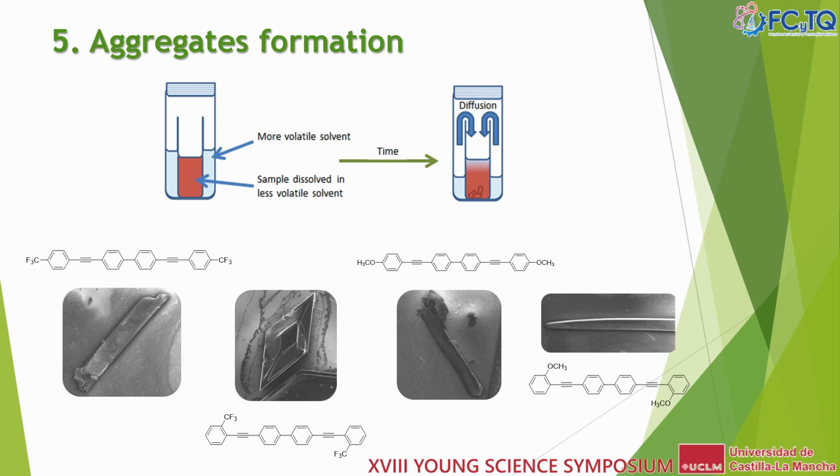Supramolecular aggregates were formed by a slow diffusion technique, which consists of dissolving a small quantity of the compound in a rich solvent and then introducing the vessel inside a bigger one filled with a poor or insoluble solvent. After some days, crystals were formed and subsequently studied by SEM or XRD.